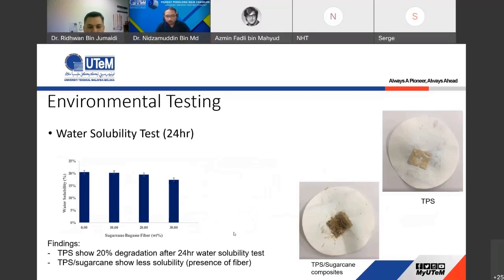Another problem with plastic products that we see is that when they are disposed of in water, as I mentioned earlier, the product tends to stay in the water for a very long period of time. This is one of the problems that leads to disturbance to the flora and the fauna in the ocean or in the river as well. So for the TPS, we did a water solubility test where we immersed the sample in water for 24 hours. What happened is the TPS started to disintegrate, and with the help of fiber, the structure becomes slightly more stable, but still it is disintegrated as well.